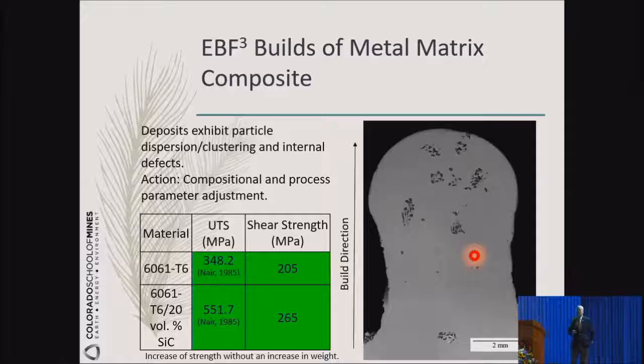All right, so this is the more hot topic these days, is that we want to use composite material for a number of reasons here, and these are the good things. You can see the UTS increase by going to a composite material. You can see the shear strength increase by going to a composite metal. So on the right-hand side here, you see a composite build. What happens there? The particulates do not disperse. That's the problem. They form clusters. And when you have clusters, you have just cut down on the effectiveness of the composite material. So then our job was saying, how do we do that?